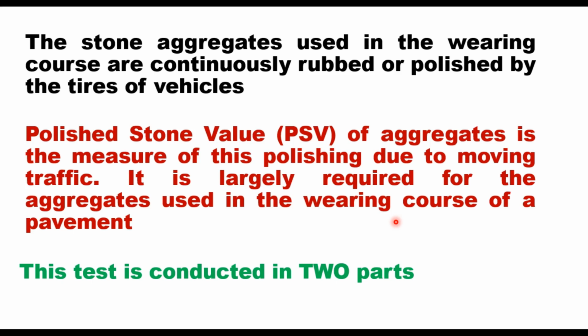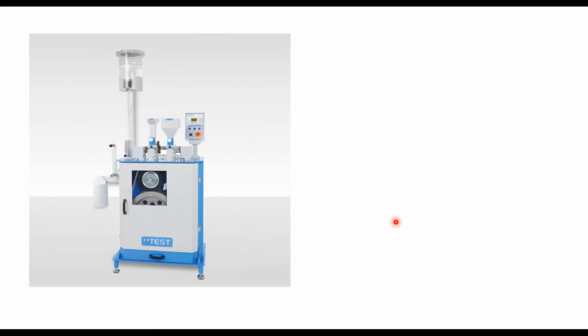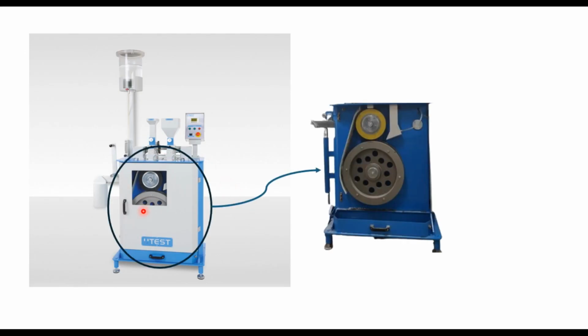So for the first part, you need an accelerated polishing machine, and this machine is like this. When you open the door of this machine, it looks like this. You have a road wheel here having a flat periphery, and when 14 specimens are mounted on this wheel, it simulates the road. This is 45 millimeter wide and 405 millimeter in diameter.